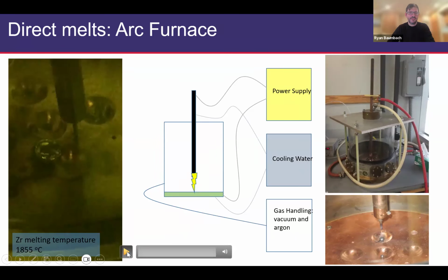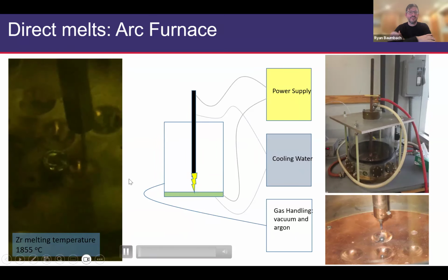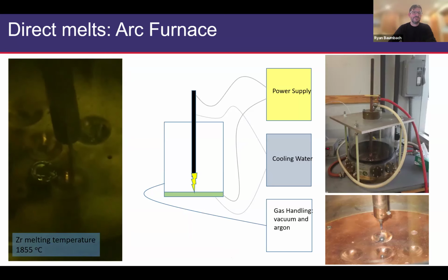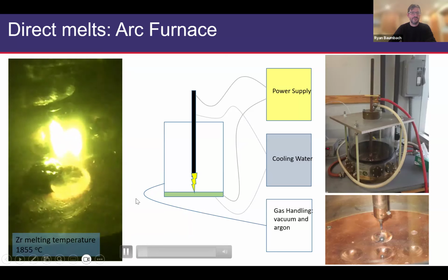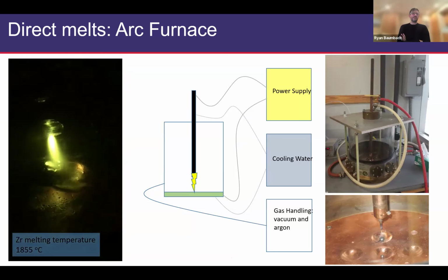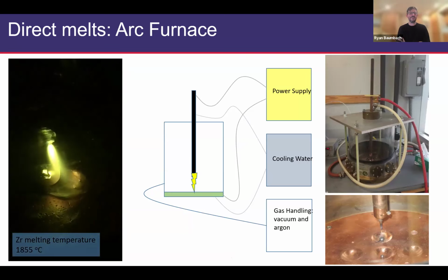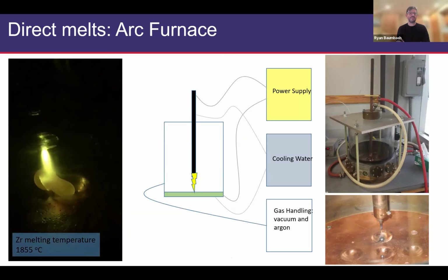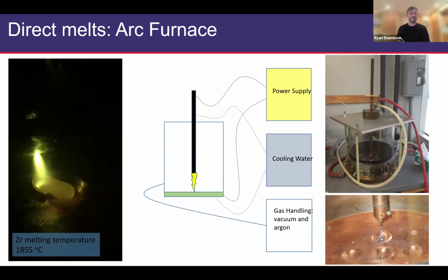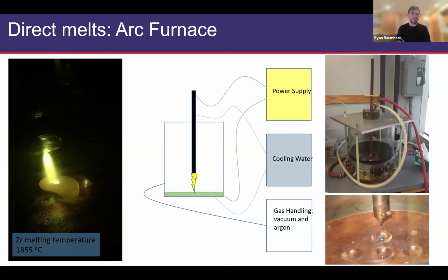I'd like to show it to you actually in action now. So that's shown on the video on the left-hand side, where we're going to strike an arc, and we're going to bring it into contact with a piece of zirconium metal. There's a few things that are worth pointing out. First is that zirconium has a pretty high melting temperature, but you'll notice that it takes almost no effort at all to melt it using an arc like this. You'll also notice that the size of the sample matters a lot, right? We're limited by the size of the arc itself, and as a result, the sample size that you can actually deal with is defined in this way. Right, so we can watch this thing sort of make its way into the copper pot.